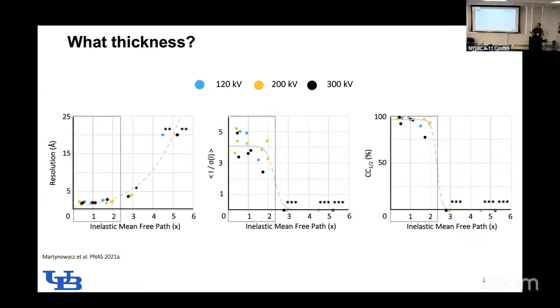Tim had this thing about being less than a micron, and I love this terrible experiment I did a while ago, where I used our Krios at different energies and accelerating voltages for that matter, and just did some proteinase K lamellae, and using an ion beam, we were able to see how thick the lamella is and what my data quality was.